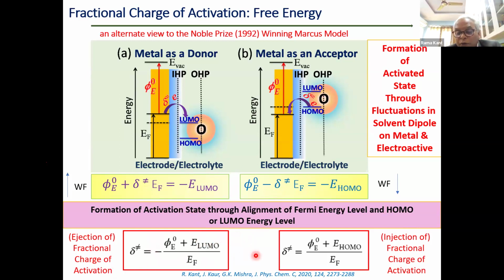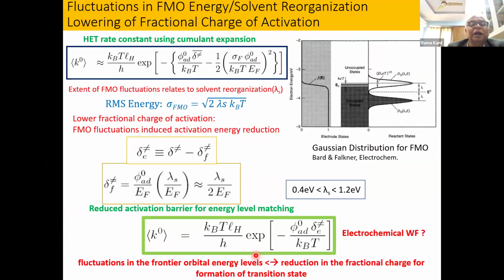in terms of the work function of the electrode, the LUMO and HOMO energy of the electroactive species, and the Fermi level of that. And then we do corrections. I'm not going into how we do it. We use the cumulant expansion method and those things. But in the final result, the first term gets modified with the second term, where sigma f represents the RMS energy fluctuation in my frontier molecular orbital. Also, in Marcus theory, you do not have a very explicit representation of the frontier molecular orbital, though for most of the kinetics we think it should depend only on the frontier molecule. So in this, the RMS energy fluctuation is related to lambda s kBT. So it is dependent on both the reorganization energy, more reorganization energy, more fluctuation, and more facile electron transfer, and the thermal energy.